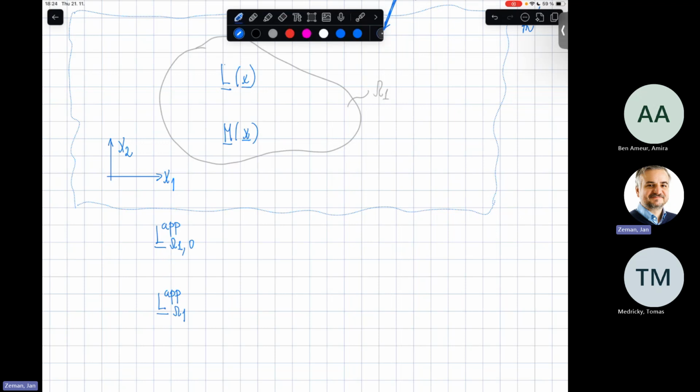And there is this relation, which I would like to write in this particular order, meaning that the apparent properties with homogeneous Dirichlet boundary conditions are an upper bound, but in the sense of this eigenvalue, so in the sense of energy which is stored in that homogenized medium. I really did my best to give you a glimpse at least of what this means.